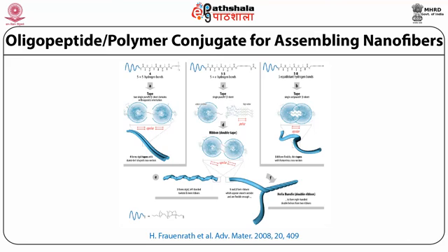They eventually can form a ribbon because each tape is helical in nature and they can twist around each other and form this helix bundle, double ribbon like structure. But in the third case, you have only a single beta sheet which is an anti-parallel tape like structure, and they form a flexible thin tape with featureless cross section.